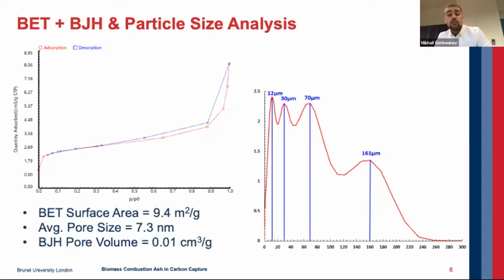In contrast, the BJH pore volume is calculated to be 0.01 centimeters cubed per gram, which is well within the reported range of ashes for both biomass and coal. The average pore diameter is estimated at 7.3 nanometers, which is consistent with the IUPAC technical report that specifies that for type 4 isotherms, the hysteresis occurs if the pores are wider than 4 nanometers, if the tests are conducted under nitrogen and 77 Kelvin, which they were.